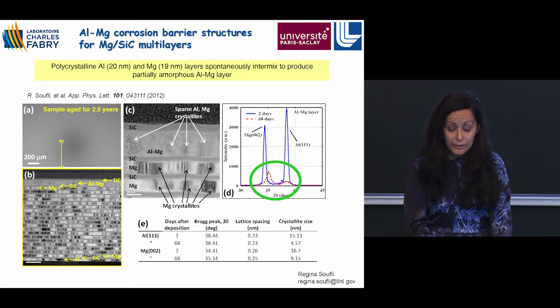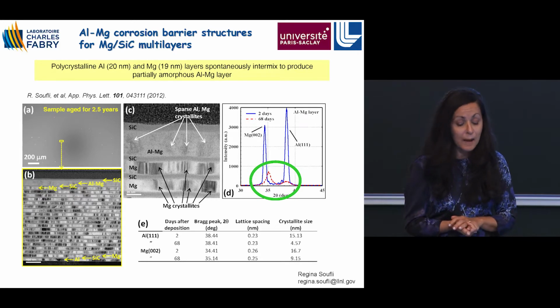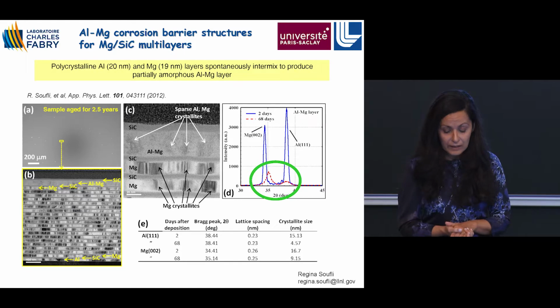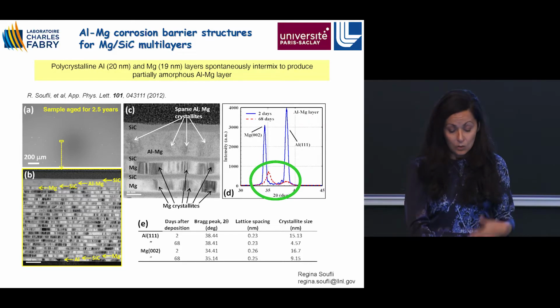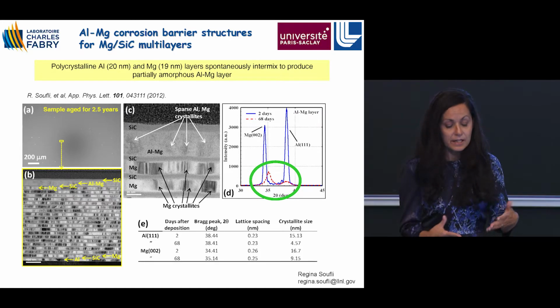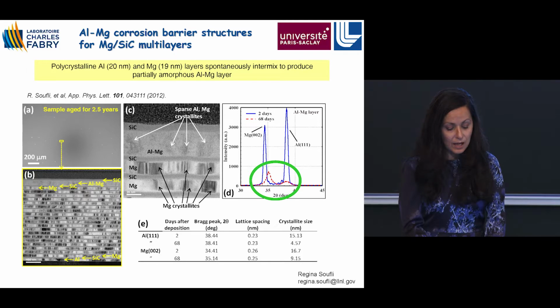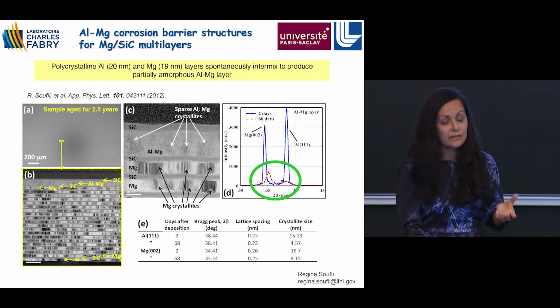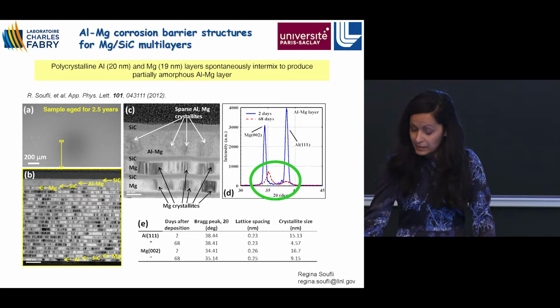So we thought that aluminum is a material that is transparent in this wavelength region, so it doesn't reduce the reflectivity, and we discovered that when it is deposited on top of the magnesium layer, the two layers diffuse into one another spontaneously. We were the first to observe this phenomenon, and from crystalline, they become nearly amorphous. So you have this nearly amorphous aluminum-magnesium layer, which is pretty thick. Here, in this case, it is about 40 nanometers. And it forms a barrier that can be pretty effective against corrosion.